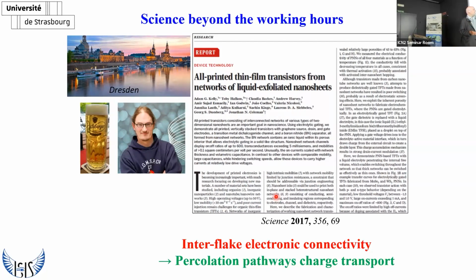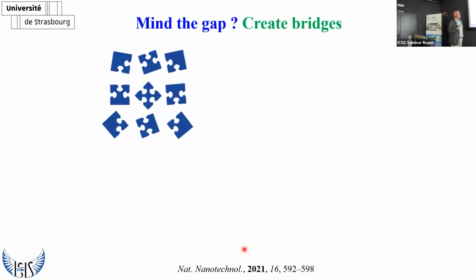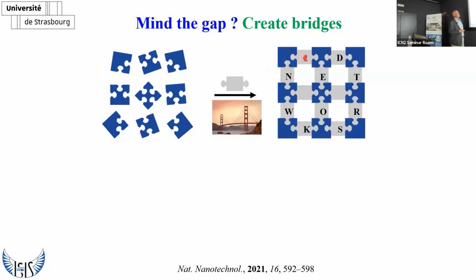And so I told him we have to find a way to create percolation pathways for charge transport, to force the charge to go from one sheet to the next one. This is something that in the field of organic-based electronics has been done, for example, by combining polymers with small molecular crystals. So at that time, Stefano Ippolito started his PhD, and I gave this as a project of his PhD. The idea, in a cartoon, is the following: if you have this kind of 2D sheet and you deposit this on a basal plane of a surface, it's like small flakes that are completely disconnected. So the concept is to use the complementary piece of the puzzle in such a way as to bind the adjacent nanosheets.